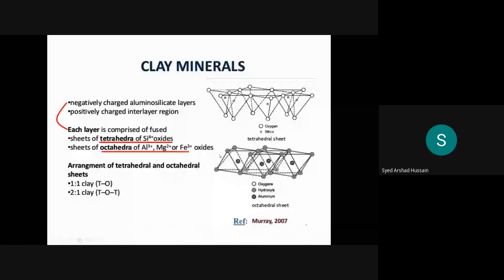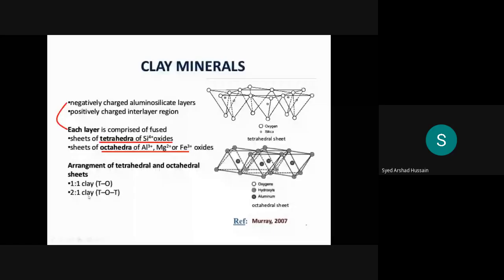The layers are mainly sheets of tetrahedra of Si4+, that is SiO4, and then sheets of octahedra of aluminium, magnesium, and ferric oxides. And the sharing or combination of these layers forms the different types. 1:1 means one tetrahedron layer, that is silica layer, and then one octahedra layer. Then 2:1 clay has a tetrahedra layer, then an octahedra, then again tetrahedra.